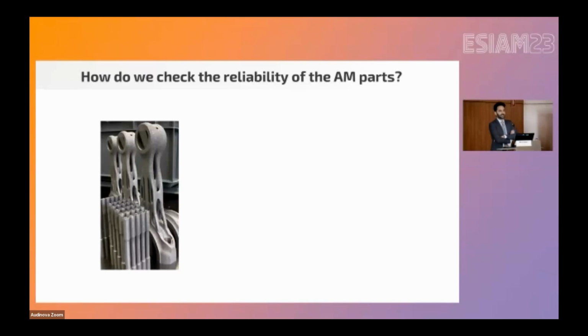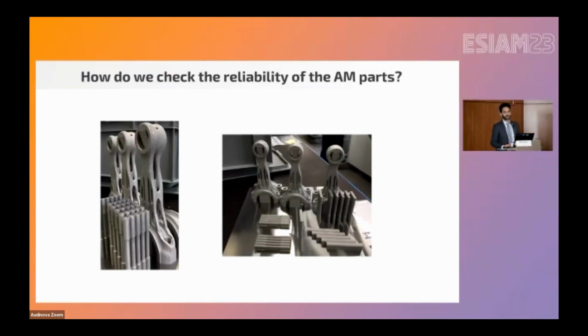But one of the most common techniques is we have our main component, and in order to evaluate its mechanical property, we just print some coupons in the same print next to the main component. If we want to make it a bit more precise, we print those coupons in different directions. We print them with excess material to do machining. But I have a question, what can be the problem with this technique? If you look at the geometry of this main component, which is a connecting rod for automotive industry, it has quite different geometry than the tensile samples that we are testing. And it has quite different size and diameter.